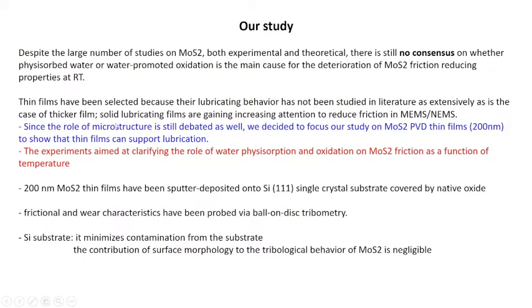properties of MoS2, and in order to do that, we deposit very thin films of MoS2 on a single crystal. We choose to deposit 200 nanometers of MoS2 in order to avoid the growth of the columnar structure, in order to see if effectively it is the presence of the equiaxed zone that supports lubrication, or if it is the presence of the columnar structure. And we also want to clarify the role of water physisorption, in order to see if it is physisorption or if it is oxidation that induces the failure of MoS2.